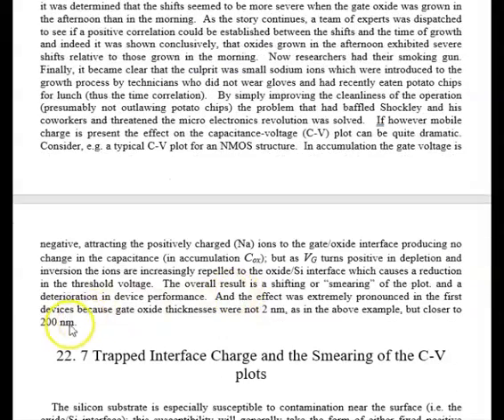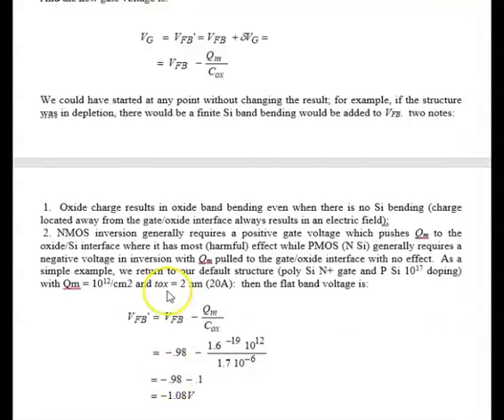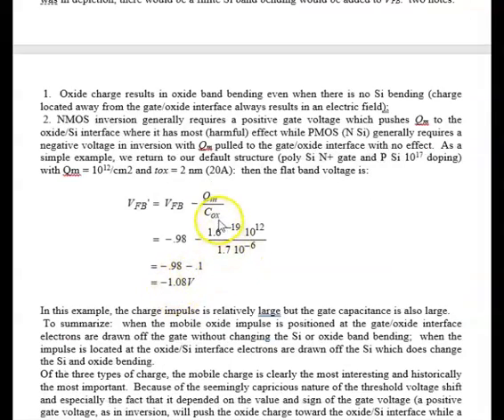And I think it's again important to emphasize the fact that we're not talking about 2 nanometers here. We're talking about 200 nanometers. So if you go back here, that C oxide is going to be reduced, not increased, but reduced because of a large gate oxide by at least an order of magnitude, or maybe even 2 orders of magnitude. So this guy is not 0.1. This could be 10. It's going to be a huge, huge effect.